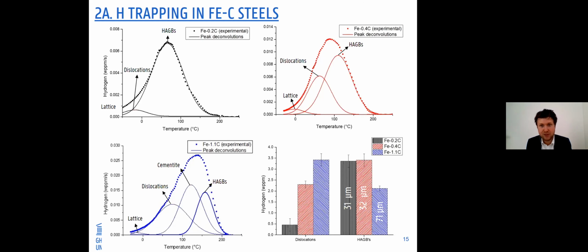Dislocations come with an activation energy of 27 kilojoules per mole and the high angle grain boundaries with 37 kilojoules per mole. What did we do to verify this? If you take a look to the right bottom, you can see that the content of hydrogen was determined under the peak by taking the integral. And you can see that the content of hydrogen trapped at these locations is increasing with increasing carbon content in the alloys.